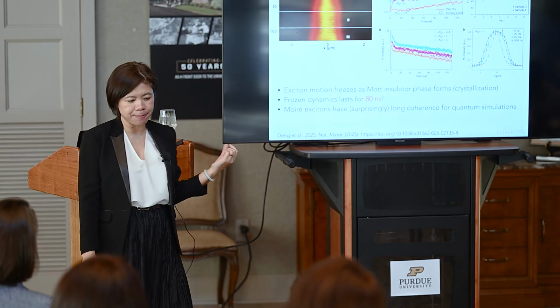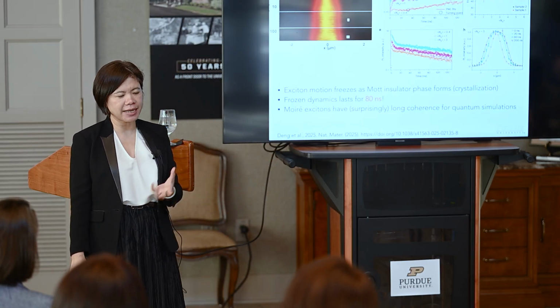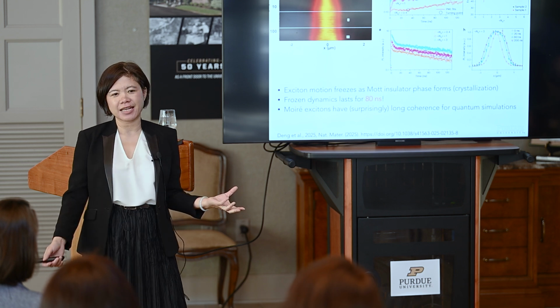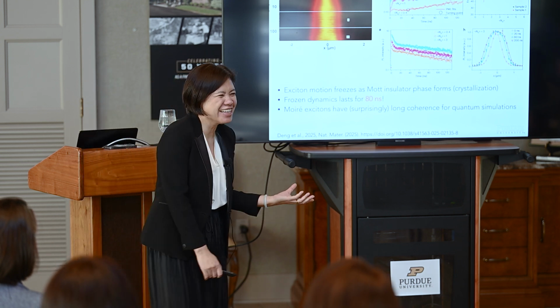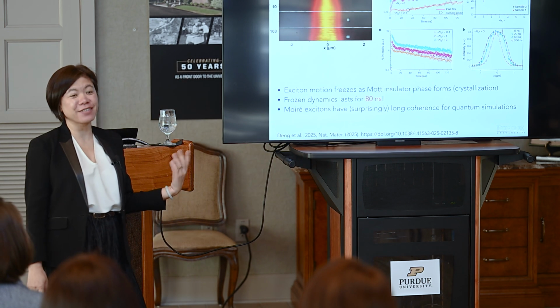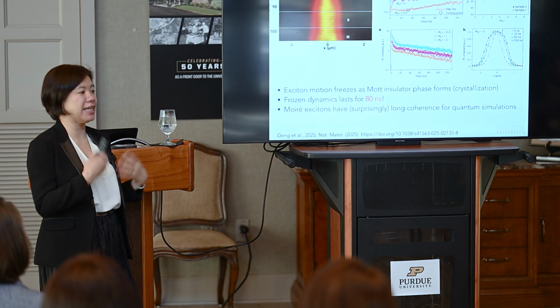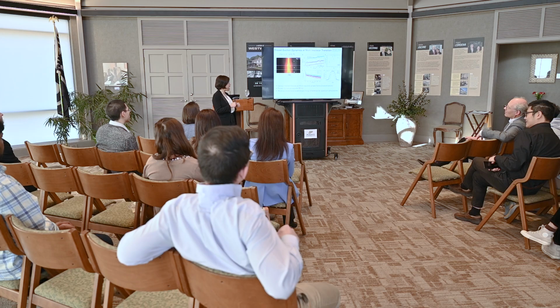And really the surprising thing is the time scale that this frozen phase lasts, which is about 80 nanoseconds. Of course, a nanosecond is 10 to the minus 9 seconds, and to many of us, that's a very short time. But for an exciton, it's a very long time because it's an excited electronic state. And so 80 nanoseconds is a large fraction of the exciton lifetime. What it says is that these excitons are coherent over this 80 nanosecond time, which would allow you to do quantum simulation on this kind of time scale.